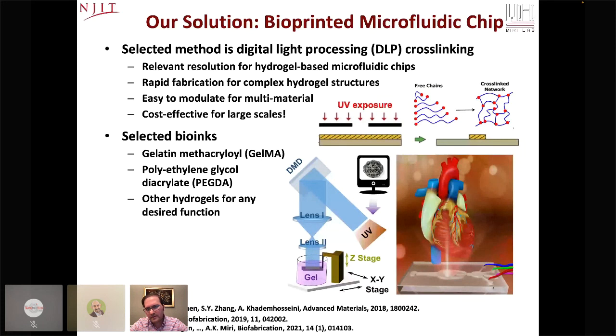In our case, as I have experience from my postdoc training, we are using a very robust, economic, and highly modular material, a gelatin-based scaffold, which we use as methacryloyl, or we call it GelMA, because it's light cross-linkable. We also use polyethylene glycol diacrylate as a stability material, or as the secondary material that helps the structure. For our main purpose, we're going to have a highly tunable system that we can apply for different applications. Gelatin would be a good candidate when you are dealing with cells, but when you don't have cells in one region, PEGDA would be a better choice.